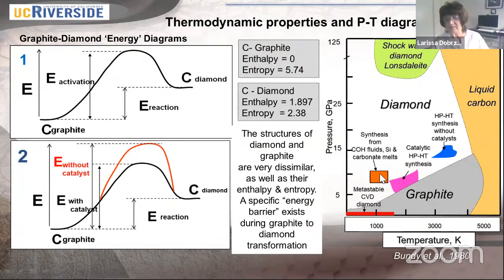Here you also see the different colored fields where diamond was synthesized from carbon-rich fluid and silica carbonate melt, and also the catalytic high pressure and high temperature diamond synthesis in industry, and also synthesis of diamond without catalyst. You see, if we don't have catalyst, we have to increase pressure and temperature significantly to convert graphite to diamond. And finally, you see metastable diamond, produced in a specific technique, chemical vapor deposition. The red line shows the stability field of the so-called production of metastable diamond.